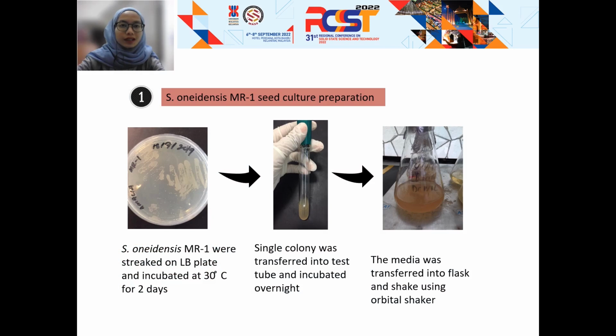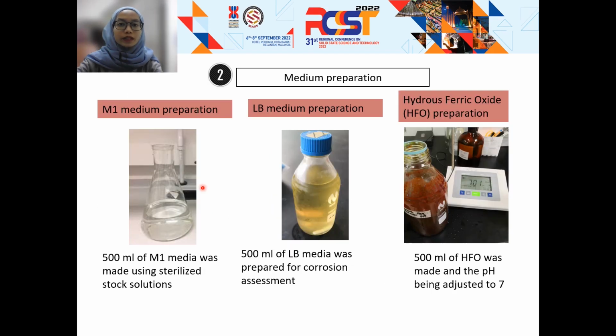Preparation of Shewanella seed culture consists of incubation of a single colony from agar plates, incubated overnight at 30 degrees Celsius at 150 revolutions per minute on a shaker. There were two media used for corrosion assessment. One is LB, Luria-Bertani, a rich carbon media, and the other is minimal salts M1 media. For minimal salts M1 media, 40 millimolar HFO was amended as the sole electron acceptor.